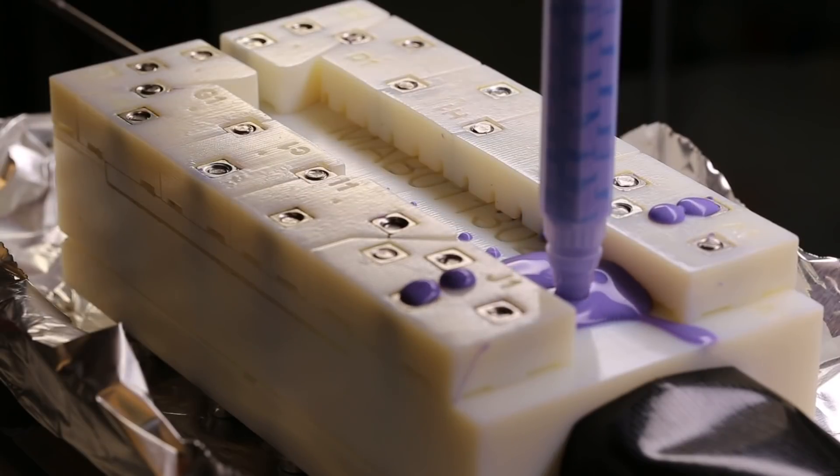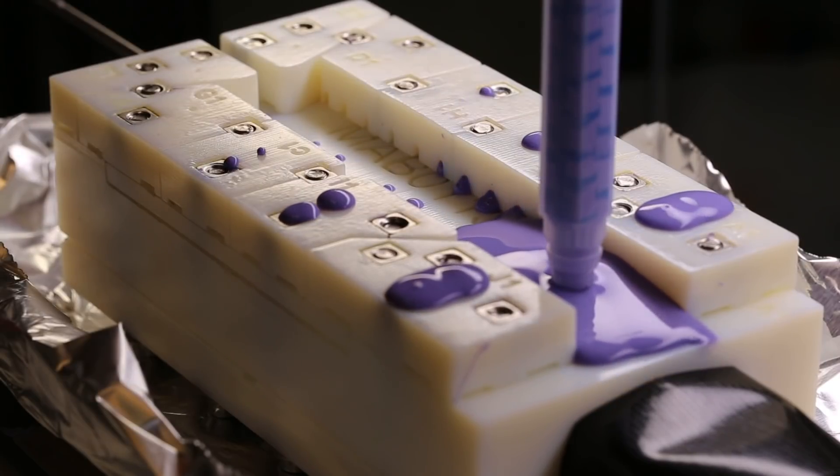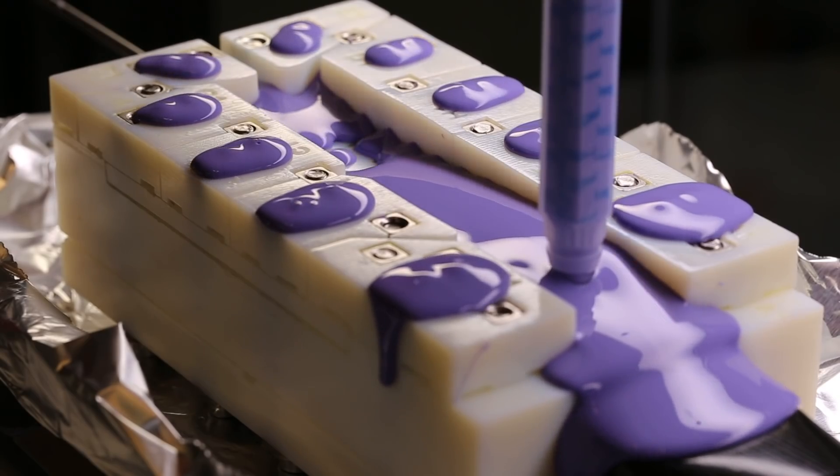We can then inject directly into the mold and wait until we see silicone popping out at the farthest sprue and no bubbles remaining.